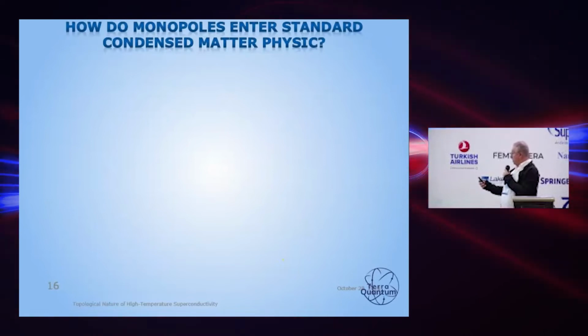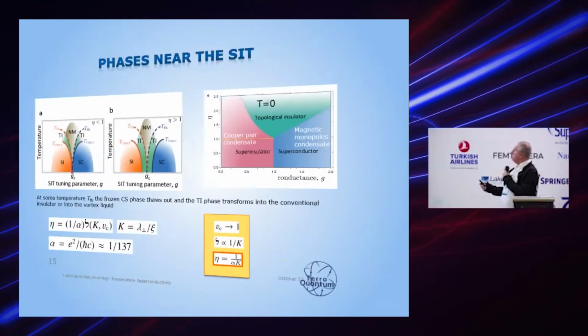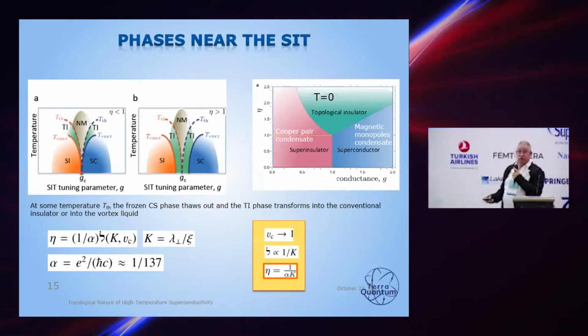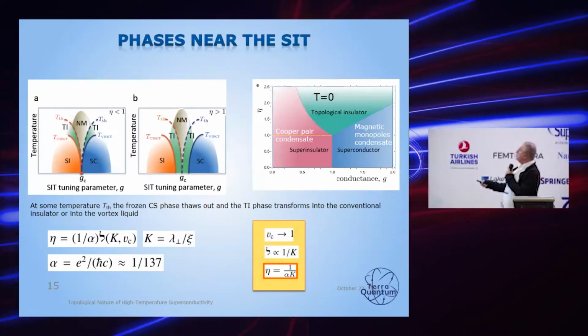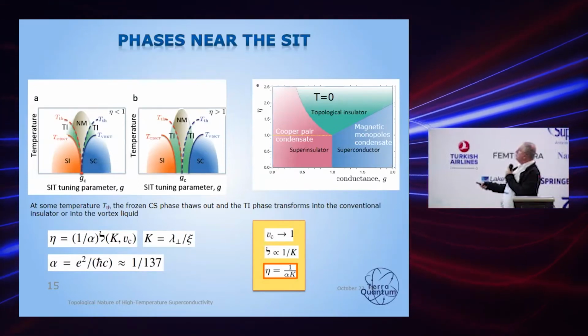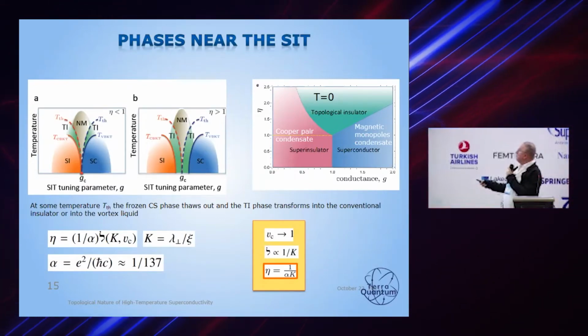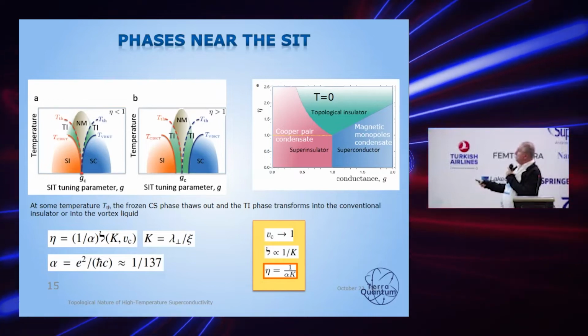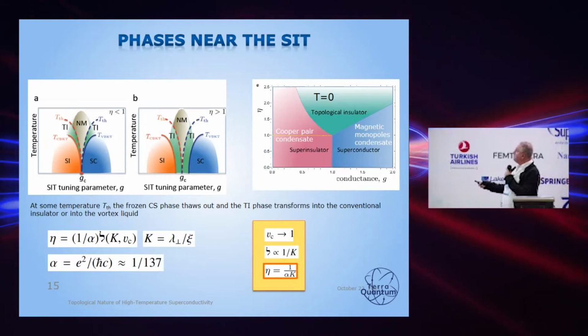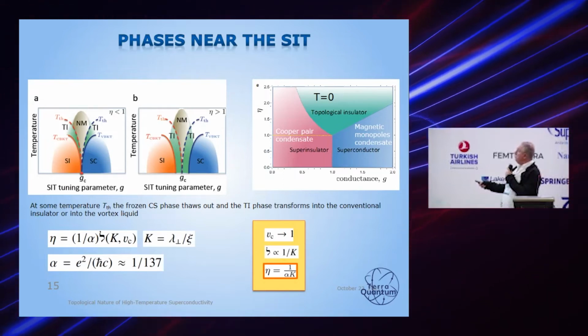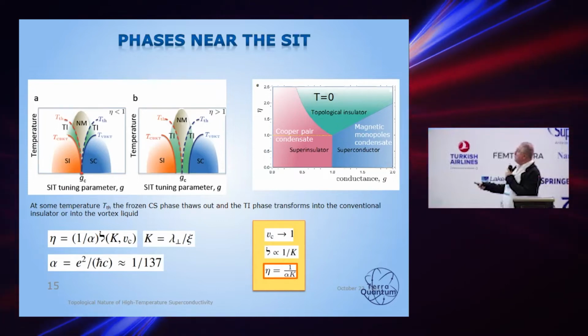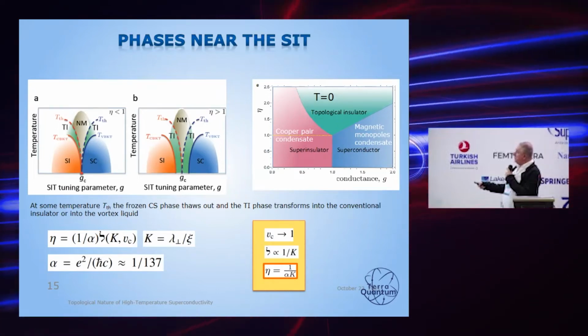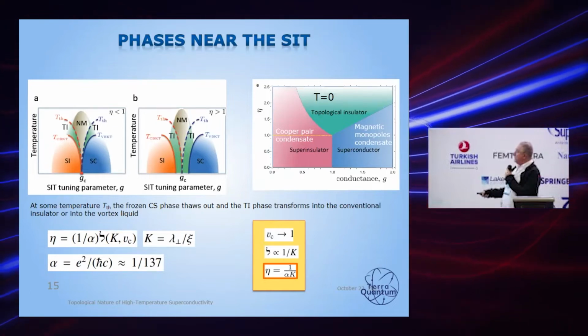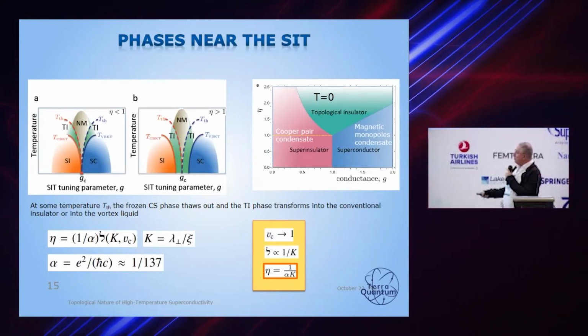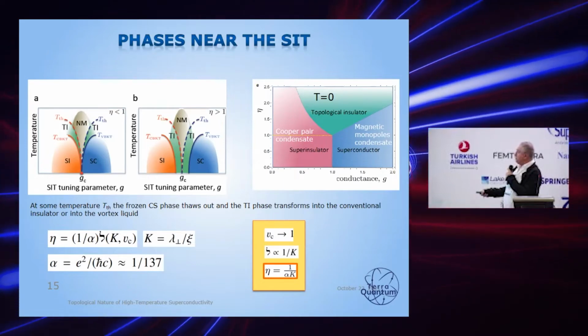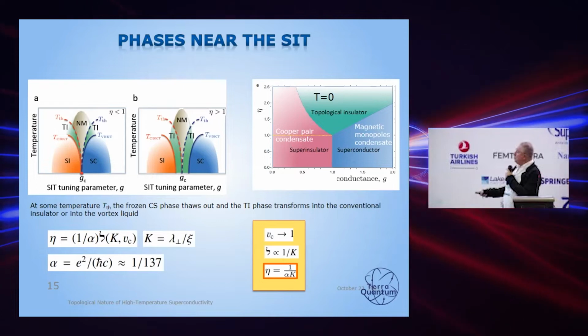So basically we have, at zero temperature, three phases. We have the superconductor, we have the super insulator, and we can have a topological insulator, which at the same time is a metal phase. And this topological insulator appears only at high values of some parameter eta. It's a beautiful parameter because it combines the strength of the quantum fluctuations and the geometric characteristics of the system, which encodes the material properties.